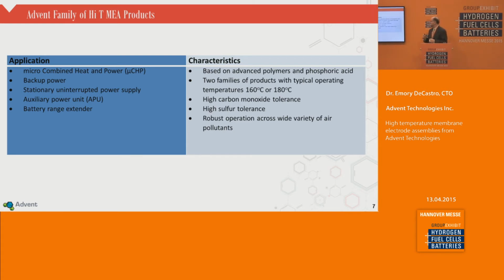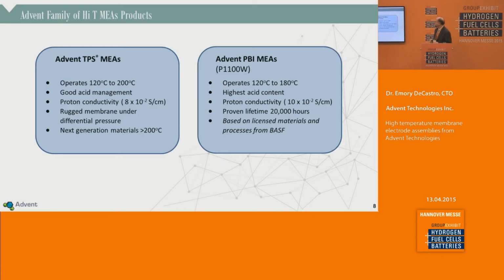Also, very good sulfur tolerance, typically up to 1 to 10 ppm of sulfur. Not ppb, but ppm, so reversible at that level. And not mentioned much, but just as important, they are also robust to impurities that come in on the cathode from the air side. So cleaning up the air feed is not that important for a high temperature system.